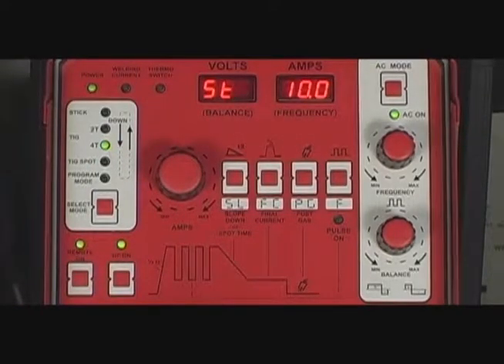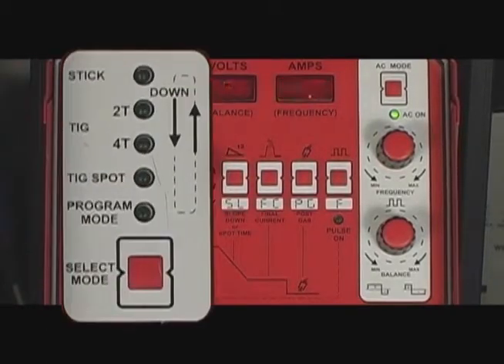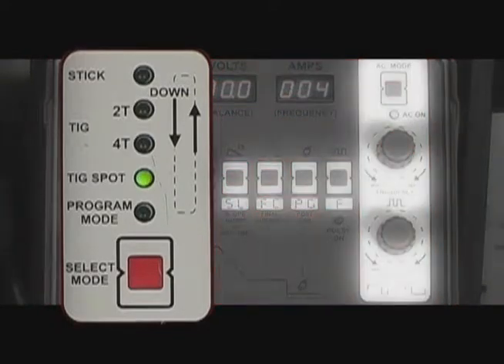Using a foot pedal allows me to manually control the slope down with the pedal, so I have to set the slope down to the minimum setting, which is 1/10 of a second. This also adjusts the TIG spot time when the machine is in the TIG spot mode.